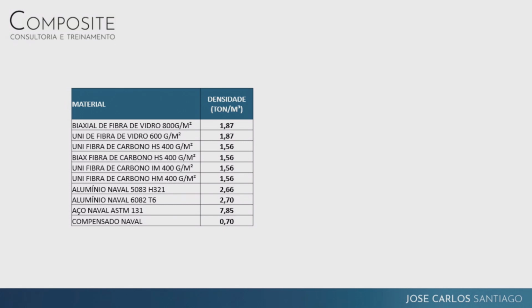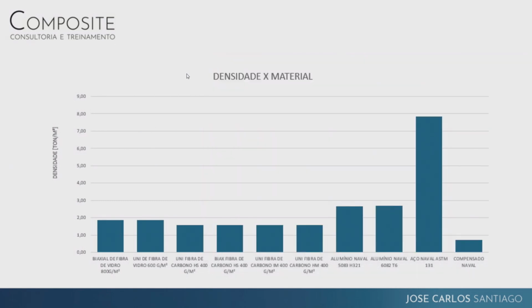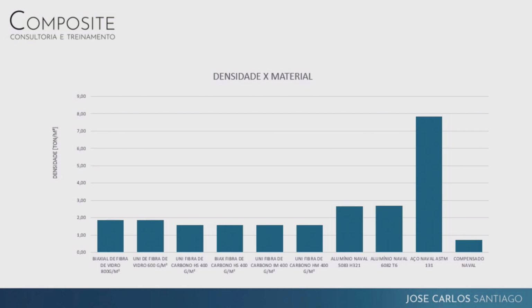Then we have a single carbon, just for us to have an idea, because the high modulus is very difficult for us to have here. There are several regulations that prevent the export of that kind of material. And some other materials that are used in boats and in ships: one steel alloy, two aluminum alloys, and naval plywood, laminated. So these fibers are laminated. They will be below 2 tons per cubic meter of density, particularly carbon fiber, and aluminums will be 2.8 and steel around 7.8 tons per cubic meter.